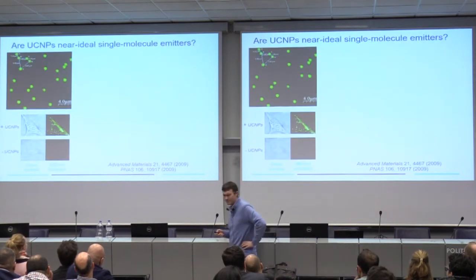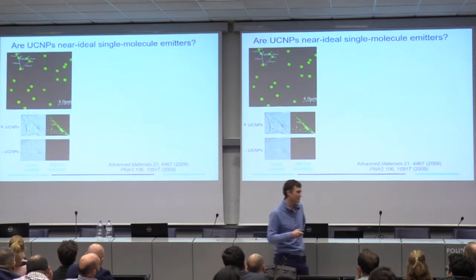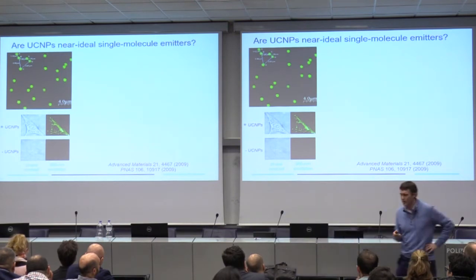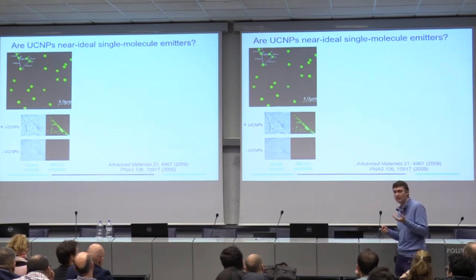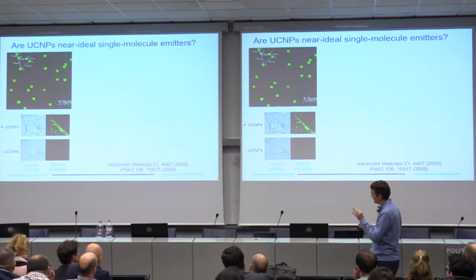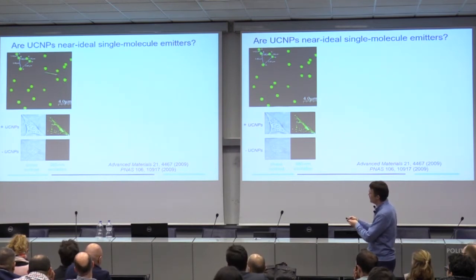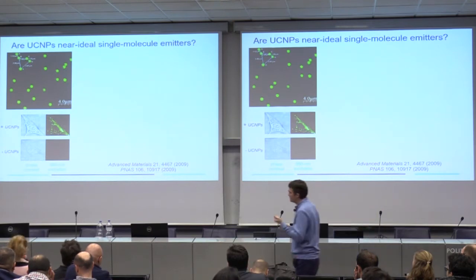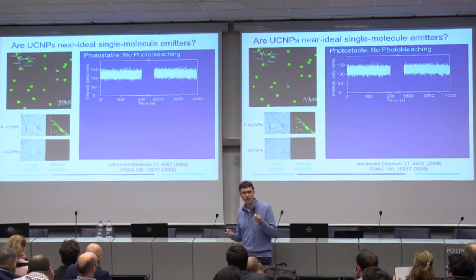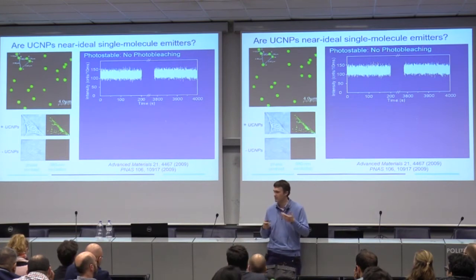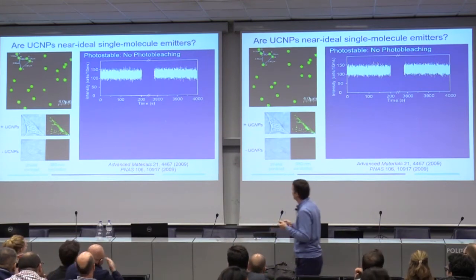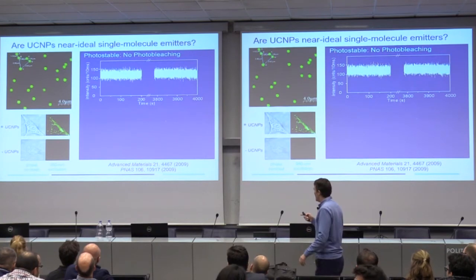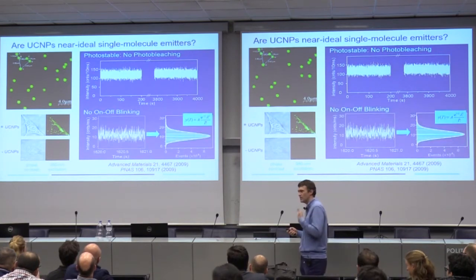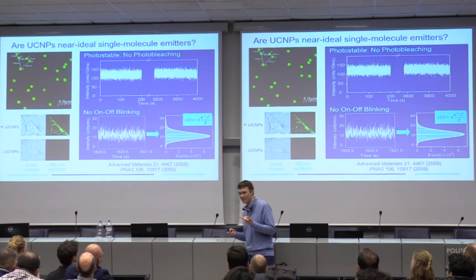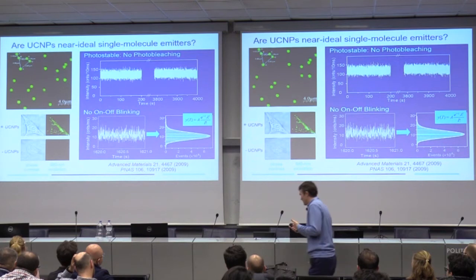It was now more than a decade ago that we first showed that these things are bright enough that you can image single particles, single upconverting nanoparticles. That's what we're showing here. These are all single upconverting nanoparticles. And perhaps most importantly, what we showed is that they never photobleach. You shine your light on them and they just keep emitting forever, at least as long as we've left our lasers on them. They also don't blink at all. So they don't bleach, they don't blink. And this got us asking whether these are getting close to near ideal single molecule level bioprobes.